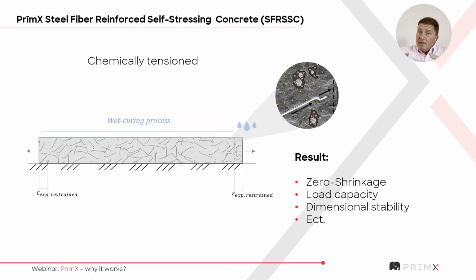Over time, this ettringite in turn changes its state and reduces slightly in volume. Effectively, we have almost like an accordion effect. The concrete starts to strengthen, reduces in volume, starts to expand slightly, starts to reduce slightly. But the net effect after about 14 to 20 days is that the concrete is around about 300 to 400 microstrains larger than when it was laid.